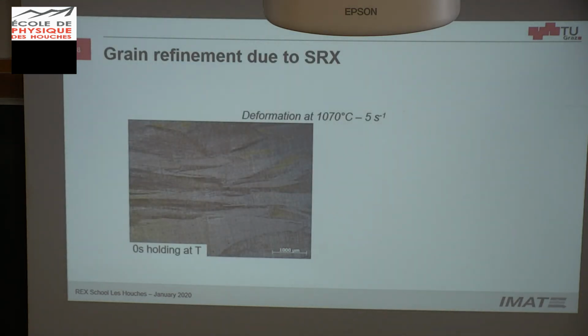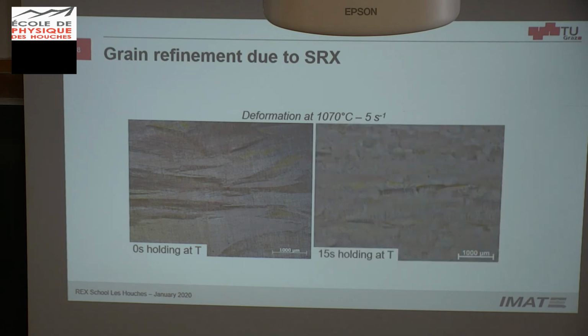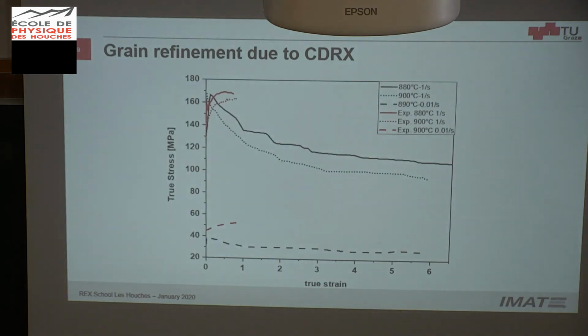And we may have grain refinement due to static recrystallization. So if I do deformation and zero holding time at very high temperatures, I have something like this or nothing. But if I wait only 15 seconds, I already have a huge amount of recrystallized grains, here more or less 40%. So that's why it's very difficult to get these kind of experiments and then to get into the phenomena. And we may have grain refinement due to continuous dynamic recrystallization.